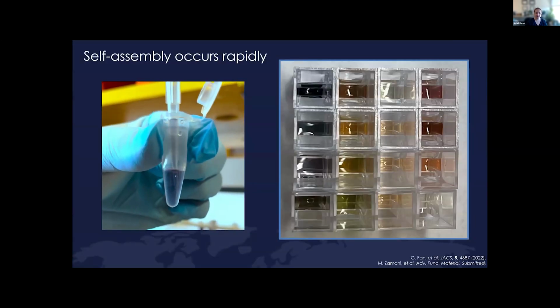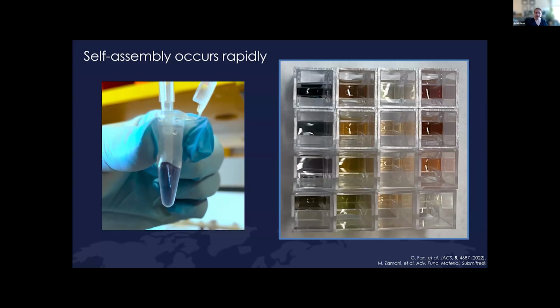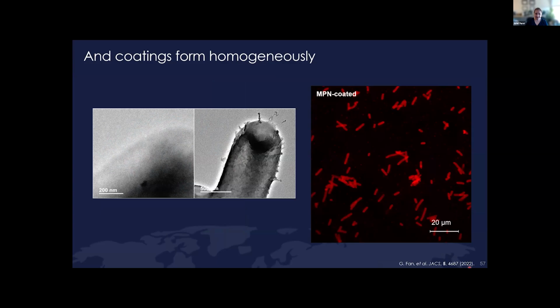If you look on the left, that blue color forming is us actually coating microbes. As soon as that metal chelates to the polyphenol, we see ligand to metal charge transfer, or the color change that results from their mixing. And the nice thing about this project is that based on the change in the metal and/or the polyphenol, we get this beautiful rainbow of different colored materials. The other great thing about this tech is we find that it coats each individual microbe uniformly. We can see that by transmission electron microscopy here, while also coating a full batch of microbes equivalently. So you can see the core shell structure of the microbe coated in these materials across this whole batch of microbes. Each individual microbe is fully coated, and every microbe in the batch is coated.